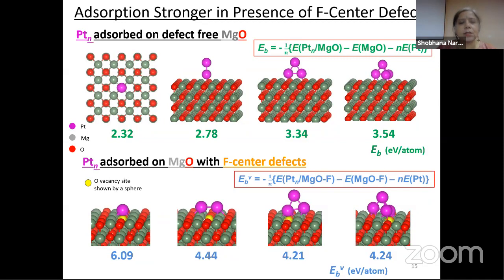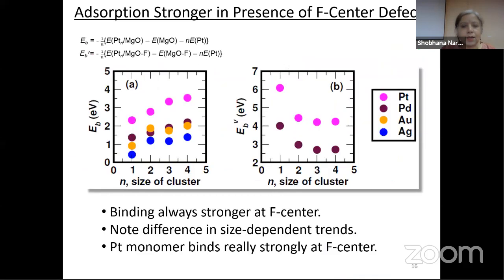So the top row shows platinum nanoparticles bound to a defect-free surface, and the bottom row shows the same nanoparticles bound to a surface with an F center, which is an oxygen defect. The position of the missing oxygen atom is shown by this yellow sphere in the bottom panel. And you see that if you have this oxygen defect, then the strength of binding increases. And this is important because if it is bound more strongly, then it is less likely to diffuse and to get sintered. And so it is favorable to have these oxygen vacancies on the substrate.